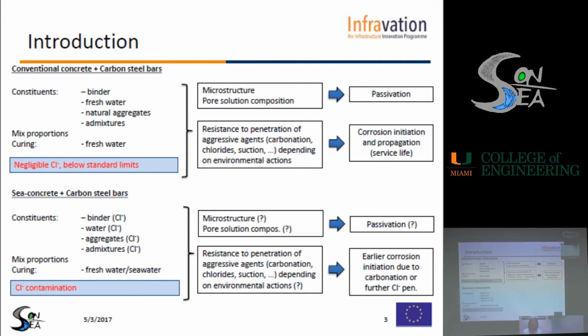What happens if virgin constituents are replaced with material contaminated by chloride? So it means if one of the constituents has a higher amount of chloride above the standard limits. The chlorides inside the concrete may affect the microstructure as well as the pore solution composition, and so the passivation of the carbon steel bar may be affected. And the presence of chloride inside the concrete may lead to early corrosion initiation and may affect the resistance to penetration of aggressive agents. The durability of sea concrete can be improved by the use of stainless steel reinforcement.